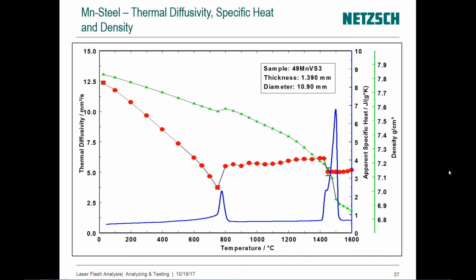No problem. Minimum thickness of the specimen will depend on the type of material. If it's a low conductive or low diffusive material, thickness can be very thin, as long as physically the specimen will be able to remain flat in the furnace, in the sample holder. There's no limitation there. As you go higher in temperature, as the diffusivity of the material increases, then at some point it will be too thin. You will have to refer to other techniques, very ultra fast pulse methods. As far as selecting the most appropriate thickness, at some point you will get in touch with us and we'll make some recommendation. But definitely you're able to use it over a wide range of thicknesses.